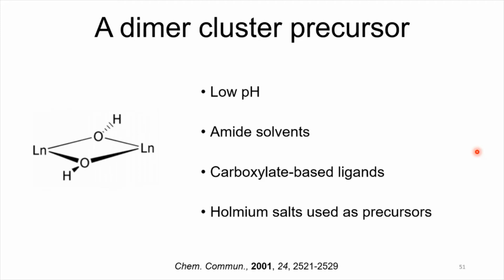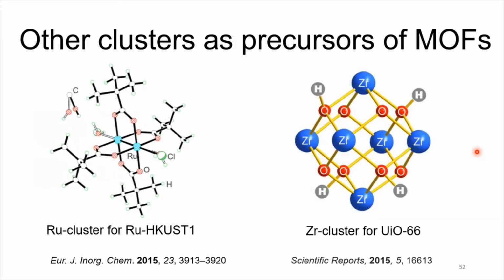The terephthalic acid comes in and substitutes those hydroxy groups, and that's why you see them in all of them. And this is not uncommon. If you look into other MOFs, for example, ruthenium MOFs are built around a ruthenium cluster, which people first modify to then build the MOF around it. Or the zirconium MOF that I showed at the beginning, you can actually synthesize the cluster first and then start modifying it to build the MOF.